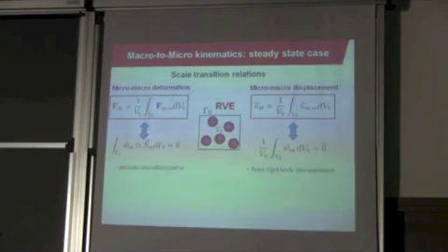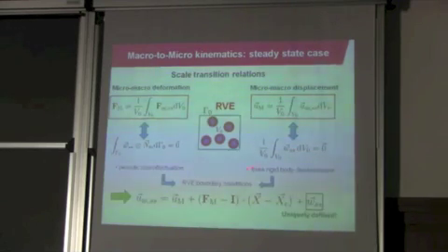which leads to the condition that the volume average of the microfluctuation field should vanish. And this condition you basically can consider as fixing the rigid body motion of your RVE. In usual computational homogenization, this condition is not added, and the rigid body motion is just fixed, more or less arbitrarily or just to zero, since there the motion is not relevant, only the strains are of importance. Okay, so this gives me the boundary conditions on the representative volume element, and with those, I can solve my equilibrium problem, which gives me the microfluctuation field.